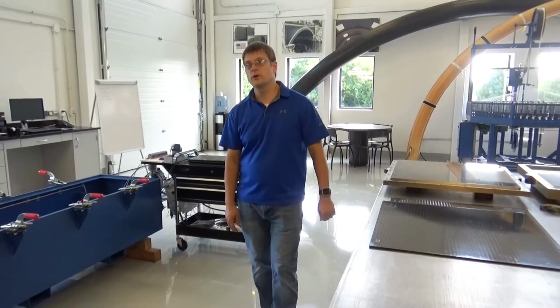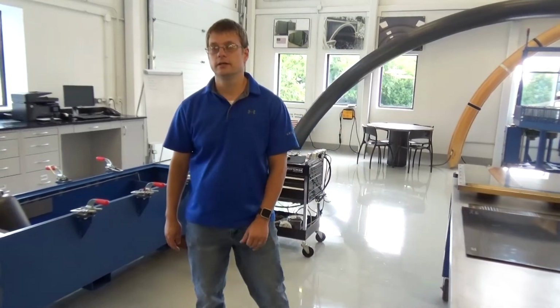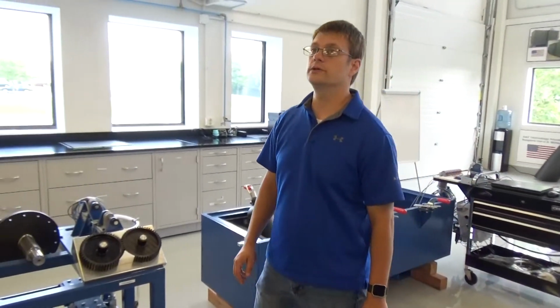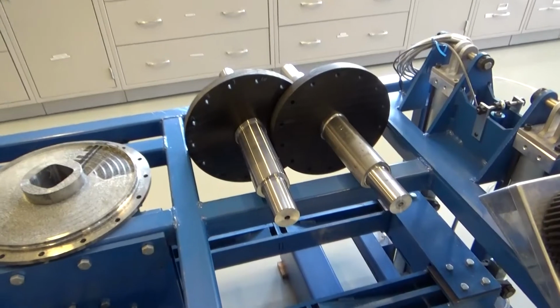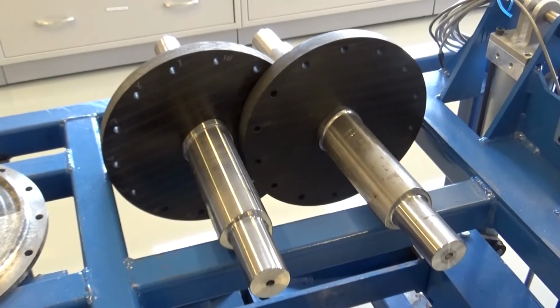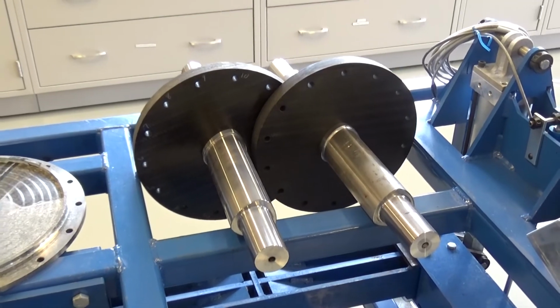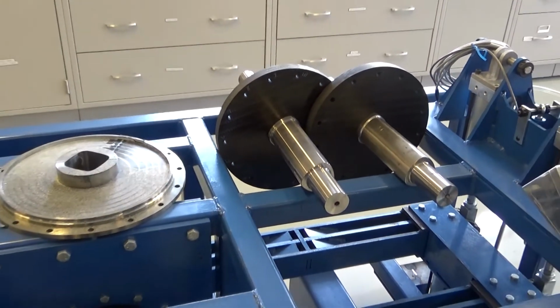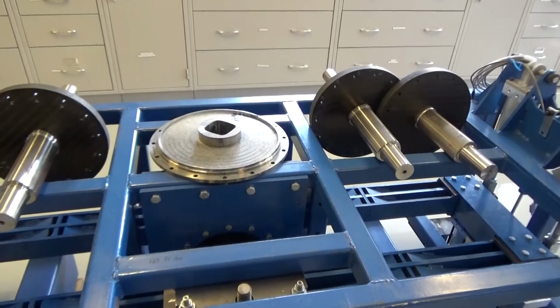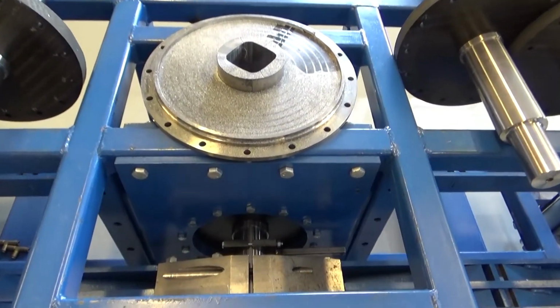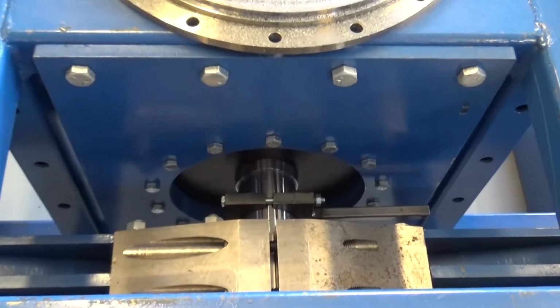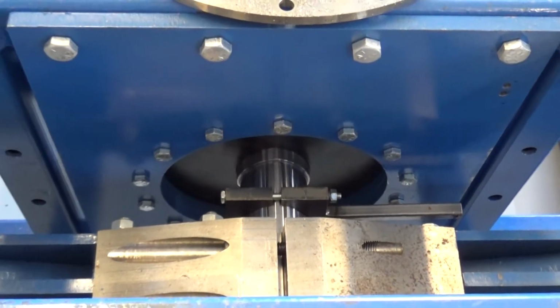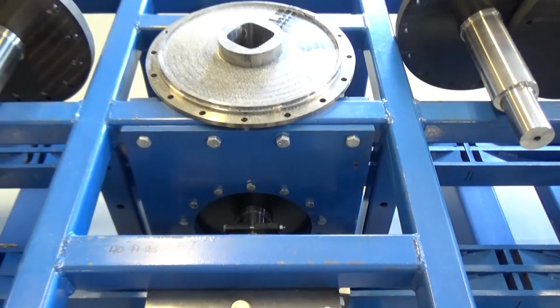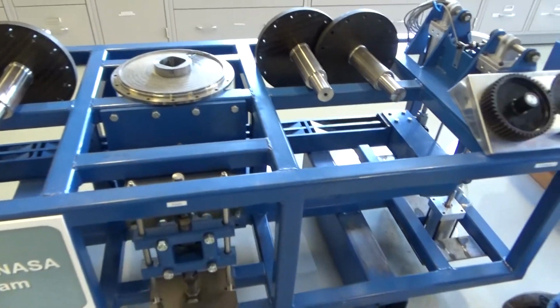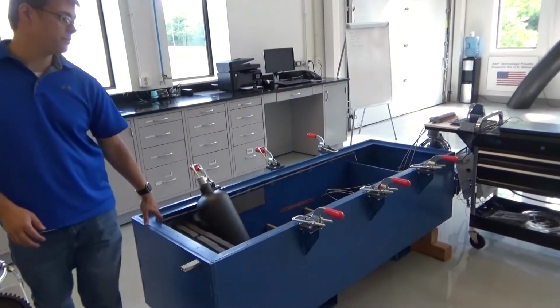We can also work with our customers to perform some simple component testing to create a turnkey layup, mold, and test facility for rapid turnaround of prototype parts. The test gear elements are 1-inch thick composite discs that are made to mimic the web of a gear system. Inside of it, you can see is a shaft, and in the actual test rig, the shaft gets rotated back and forth. And we calculate and measure the overall rotation angle over several thousand fatigue cycles. This gives us indication and test results as to whether we're getting any sort of failure at the composite to metallic interface.